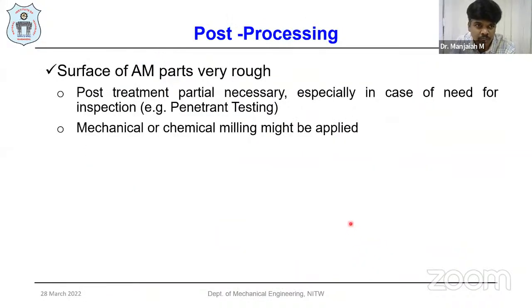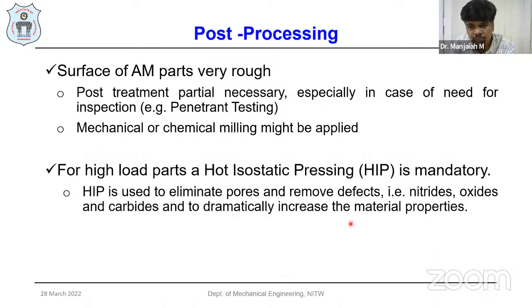Post-processing is required to minimize the very rough surfaces, and post-treatment is partly necessary, especially in the case of inspection like penetrant testing. Mechanical or chemical milling might be applied to minimize this rough surface. And for high load parts, we have to go with the HIP process. It is mandatory to eliminate the pores and remove defects like nitrides, oxides, and carbides that dramatically increase the material properties.